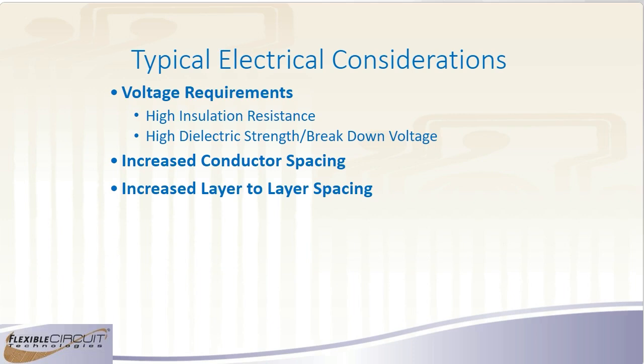Layer to layer, you're going to also have to space that out. With polyimide, typically if you're 1 mil or thicker with your polyimide layers, you probably don't have to worry about that too much. It's only if you have 0.5 mil or less for your polyimide layers. We typically don't see any issues with 1 mil or thicker as far as layer to layer. I can say that in 40 years, I've never seen a layer to layer dielectric breakdown in a flex circuit because of the polyimide. But I have seen them occasionally. It's rare, but you see them occasionally with 0.5 mil polyimide. So if you do have high voltage, you're probably going to want 1 mil or thicker for your layer to layer separation.